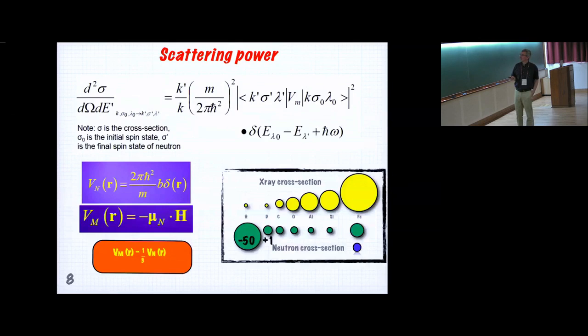Just quickly, this is like a basic formula, and you're looking at some scattering strength of your material and the two states you're scattering from, or energy. With synchrotrons, you interact with the electron cloud, with X-rays. And so as you go through the periodic table, that strength increases. So if you were looking at hydrogen diffusion in iron, it would be almost impossible to see this hydrogen. So you wouldn't get the diffusion you really want.